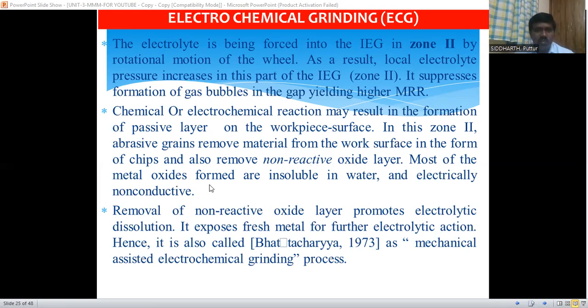Most of the metal oxides formed are insoluble in water and electrically non-conductive. The removal of the non-reactive oxide layer promotes the electrolytic dissolution. It exposes the fresh metal for further electrolytic action. Hence, it is also called a mechanically assisted electrochemical grinding process. So whatever passive layer is formed, that passive layer is removed by means of this mechanical reaction. That's why it is a mechanically assisted electrochemical grinding process.